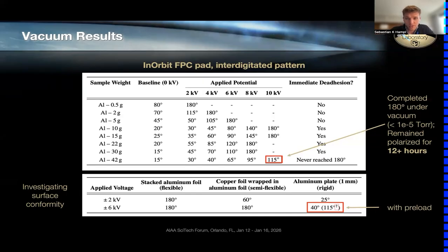So that points to residual polarization being much higher, or much more pronounced, in vacuum. We also investigated surface conformity, which is another factor that we found to be very crucial during the experiments. We used materials of different rigidity levels, ranging from aluminum foil, which is super conforming and flexible, to an aluminum plate, which is rigid. And we found that it is much harder to generate an electroadhesive force if the surface conformity isn't close to perfect. And then we tested preloading on the rigid body, and that increased performance by quite a lot because we forced surface conformity between the plate and the electroadhesion pad in this case.